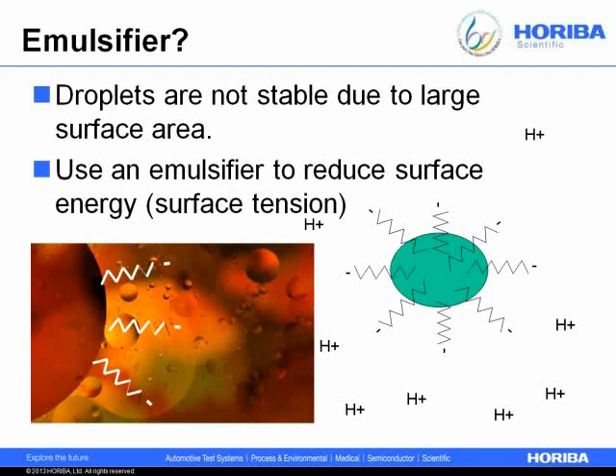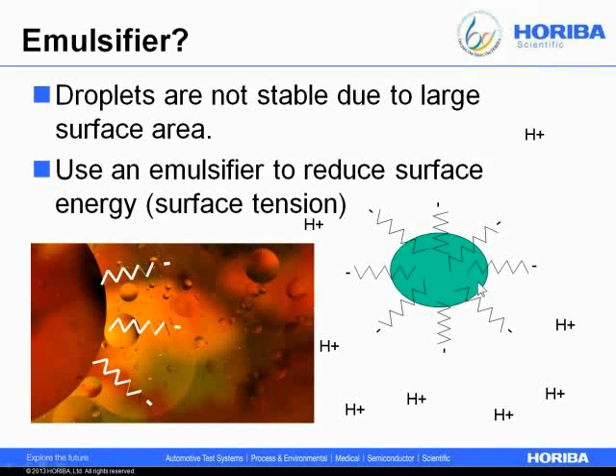Often you start adding other materials. If you think about an emulsion droplet, you might add a surfactant — something with an oily tail and a polar head, which may be negatively charged with a counter-ion. A bunch of these surfactant molecules arrange around the surface of the droplet, presenting an oily surface to the oily phase and a polar surface to the aqueous phase. The surface energy of this droplet becomes very small. The same idea is shown schematically with a green oil droplet in water, with cations floating around in the suspension.